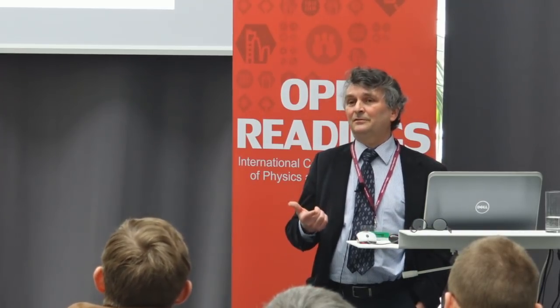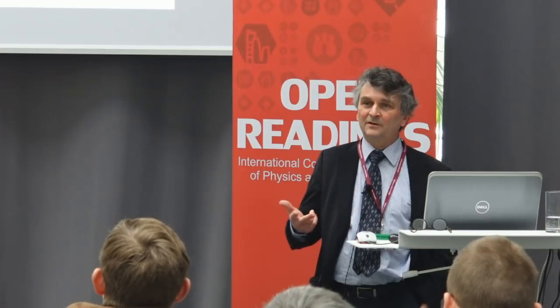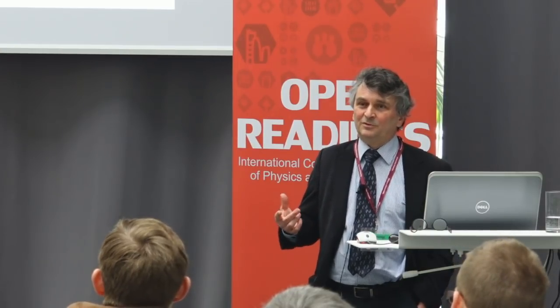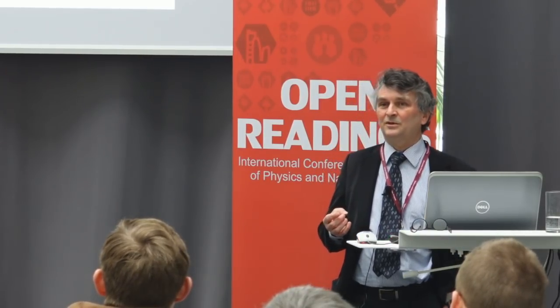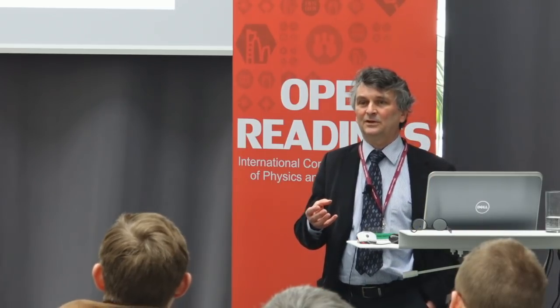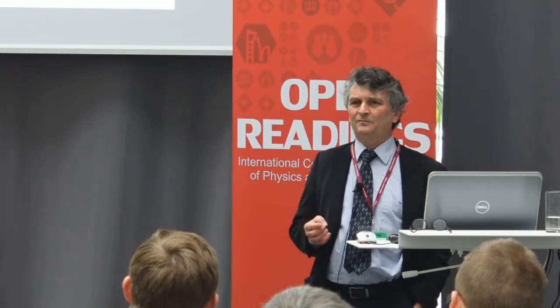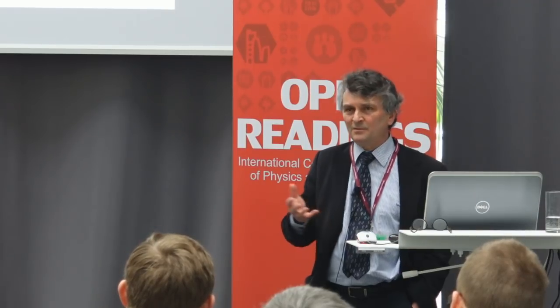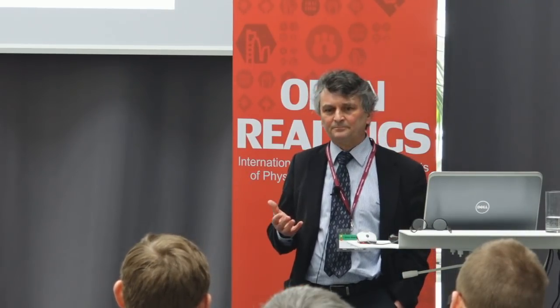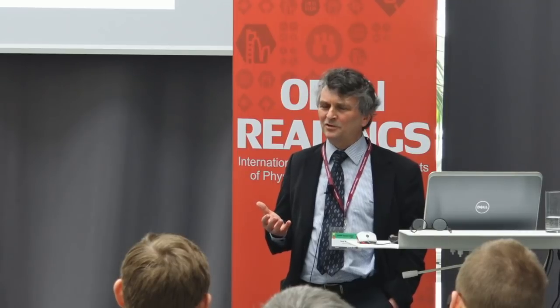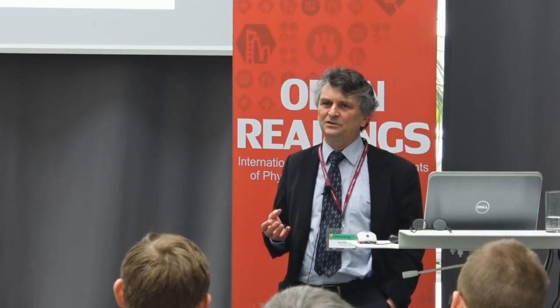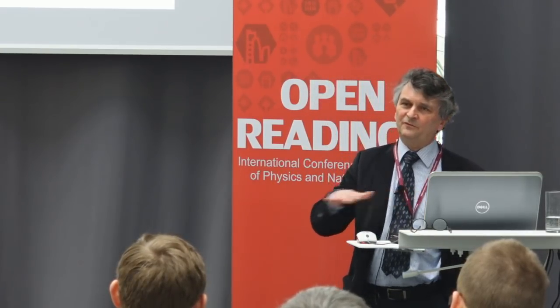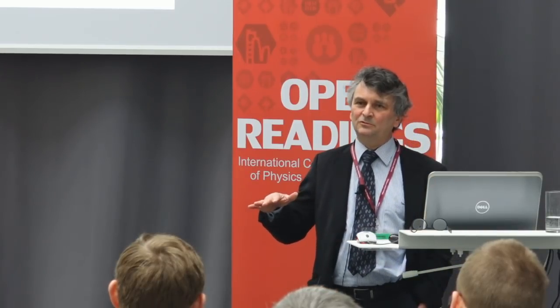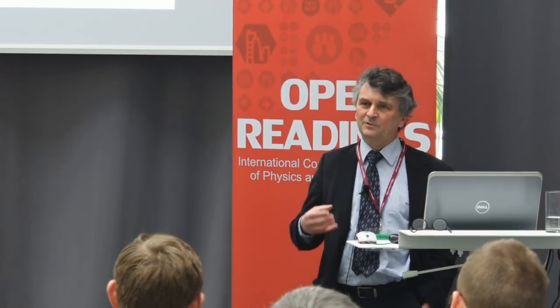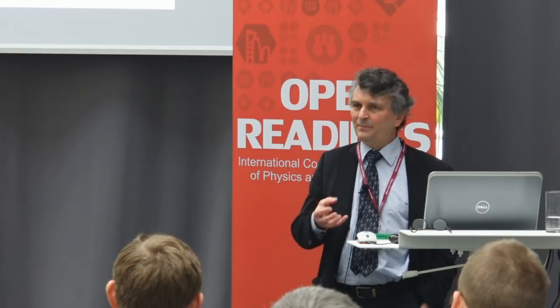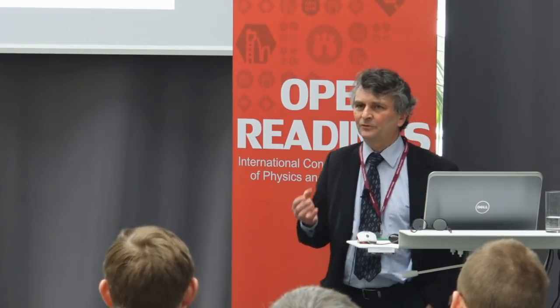And then indeed, silicon is a non-polar semiconductor. III-Vs are polar. So that is the other problem. You create domains, and it's not so easy to get rid of that. So there are lots of problems. But as I mentioned, in the case of indium phosphide, there has been remarkable progress in recent years, but never with just flat 2D growth onto a surface. It's always with some sort of patterning or quantum dot approach.